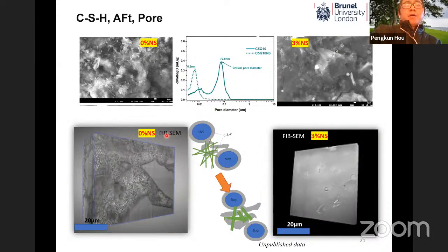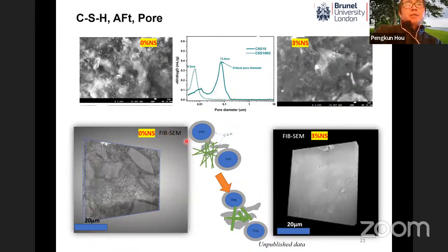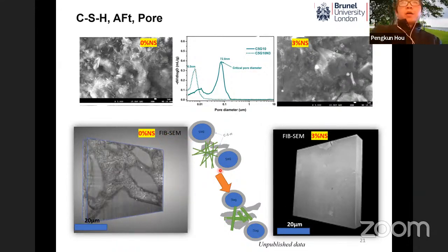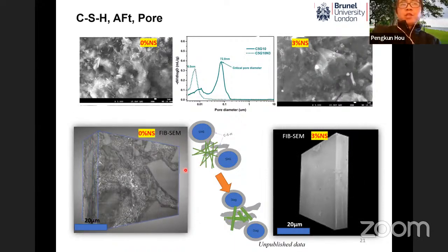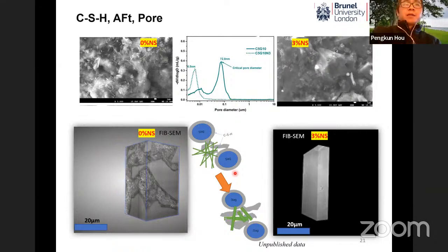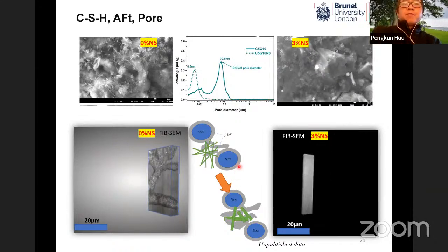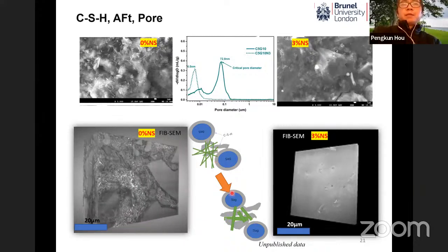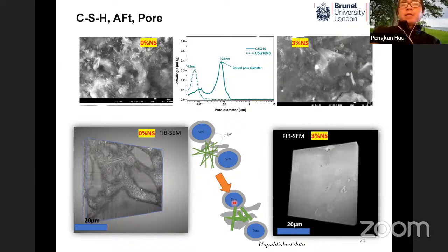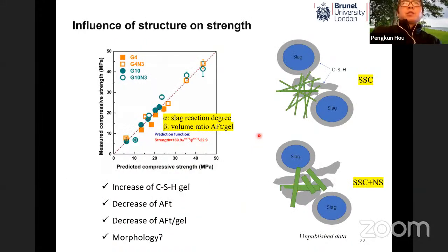Then we did the focused ion beam SEM tests. From these, we can more clearly see how the microstructure changed with the addition of nanosilica. So this can be further used to verify the structure model before and after nanosilica addition. So we can see the increase of CSH, the decrease of ettringite, and decrease of AFt to gel. I think I made a mistake, right? So decrease of ettringite to gel ratio.